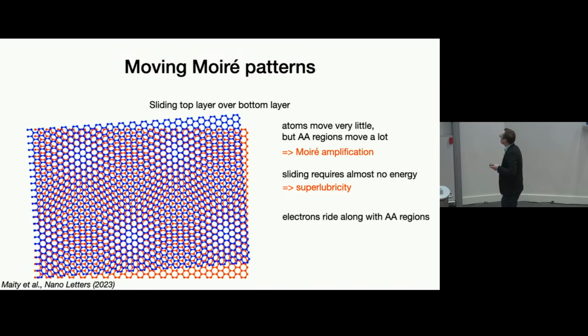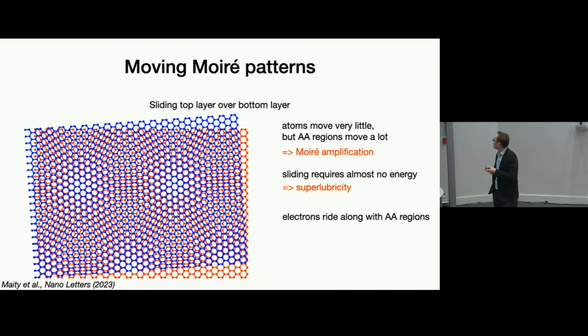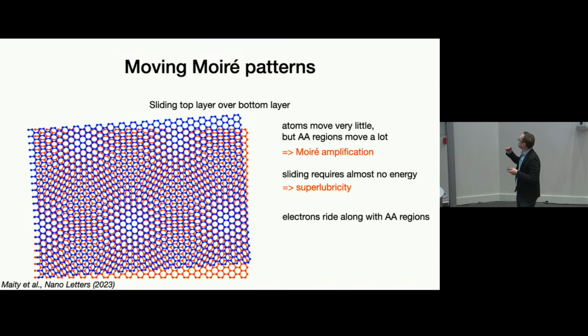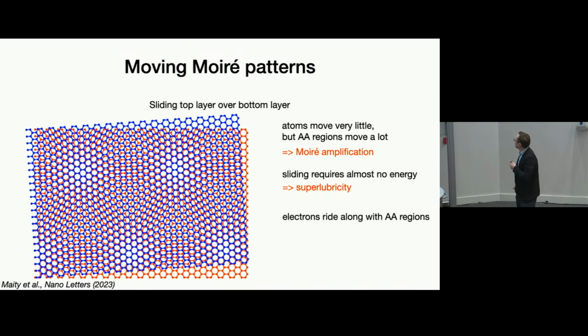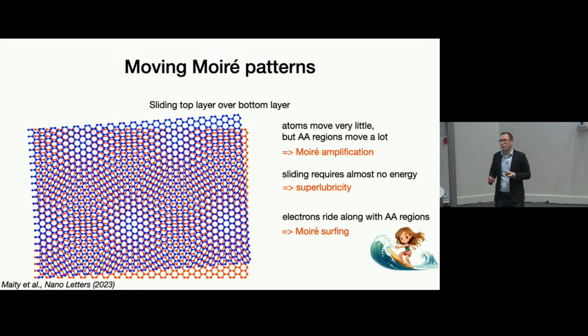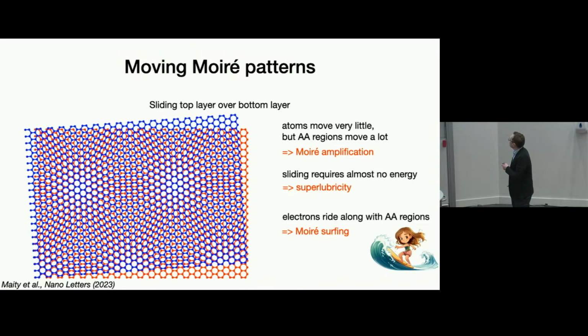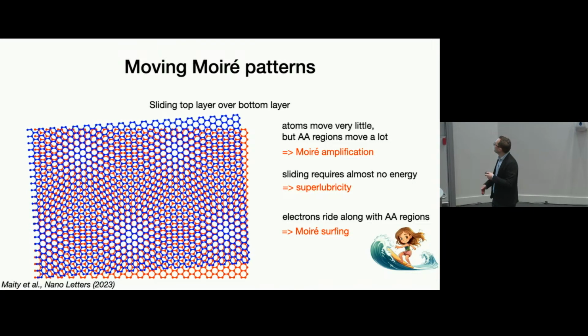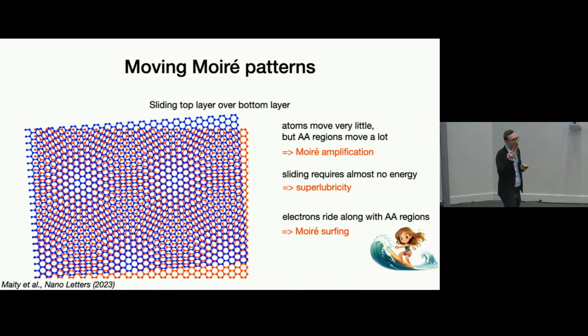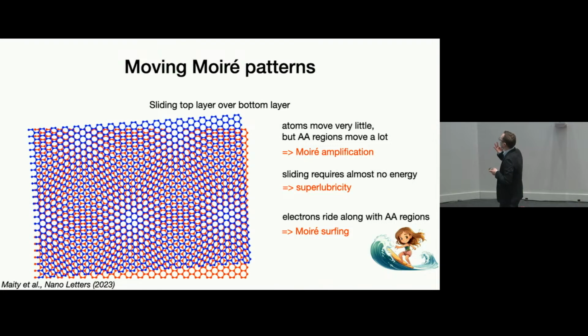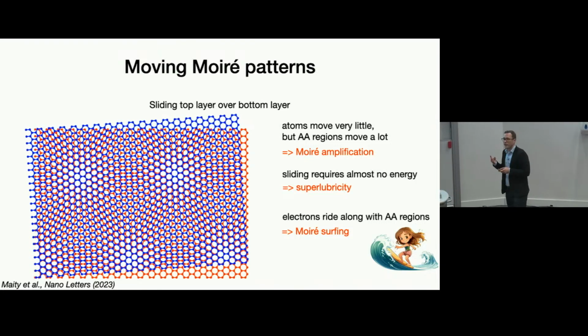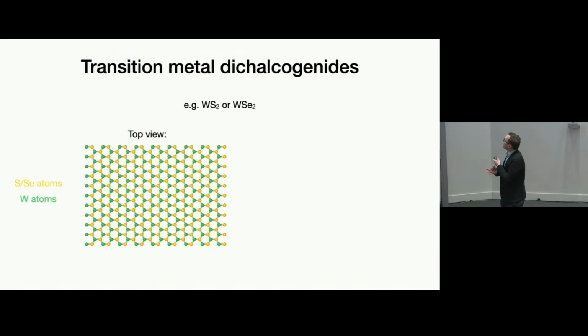The last observation is about the electrons in the twisted bilayer graphene. So we know that the electrons actually follow the Moiré pattern, so they prefer the AA regions. And this is a phenomenon that we call Moiré surfing. So much like a surfer that is transported along by an ocean wave, the electrons are transported along with the moving Moiré pattern. So these are three observations, and they would turn out to be quite useful in explaining our work on another type of Moiré material, which is not based on graphene, but on the transition metal dichalcogenides.